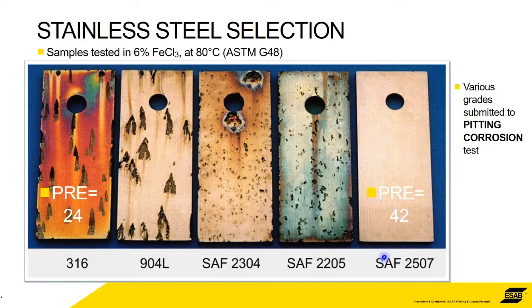So all of these samples from the various alloys have been submersed in this 6% ferric chloride solution at 80 degrees. It's a nasty corrosive solution, and you can see the effect. I don't know the amount of time, but they've all been in there for the same amount of time. The effect on the 316, which has a PRE of 24: you can see the whole surface has decayed. It has suffered lots of corrosion, and you can see these areas where pits have started to form. The corrosion's broken through the surface.